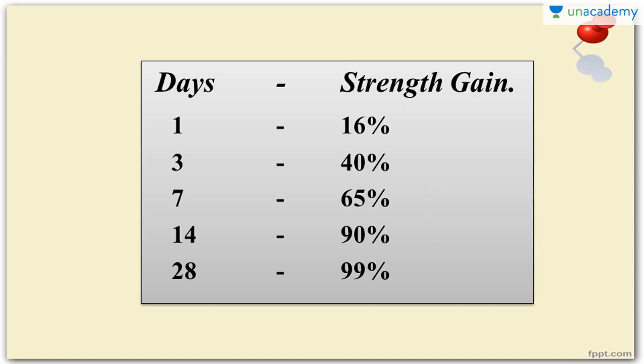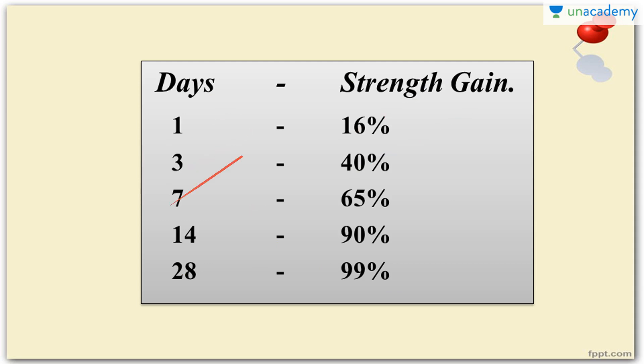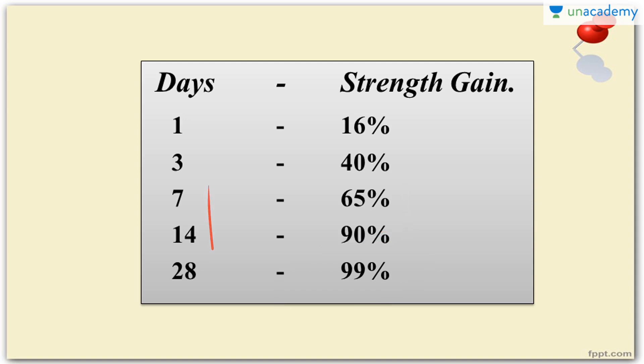In the case of normal concrete, you may wonder why we take the strength test at 7 to 28 days, and why the 28-day test result is very important. From this tabulation we can see the gain of strength over days: 1st day — 16%, 3rd day — 40%, 7th day — 65%, 14th day — 90%, 28th day — 99%. After the 28-day period, the concrete matures to its ultimate strength. You can see a big jump from 65% to 90% in one week, and then 90% to 99%. This applies only to normal concrete, not special concrete.